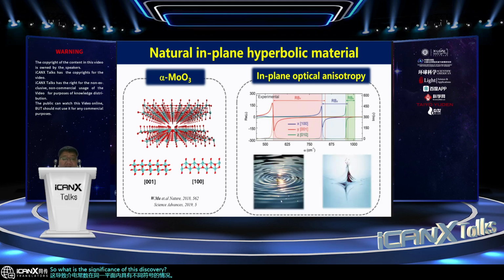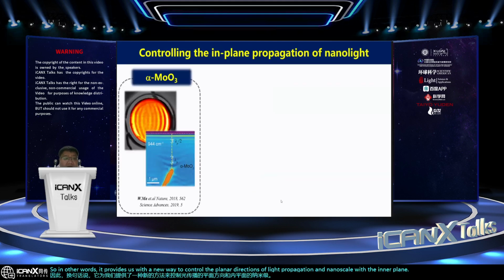To put it simply, if we liken the typical polariton propagation to water waves, these materials allow us to give these waves specific directions within the plane, rather than spreading uniformly in all directions. So in other words, it provides us with a new way to control the planar directions of light propagation at the nanoscale within a plane. Using near-field imaging techniques, we have indeed observed the anisotropic propagation of the polaritons within MoO3.